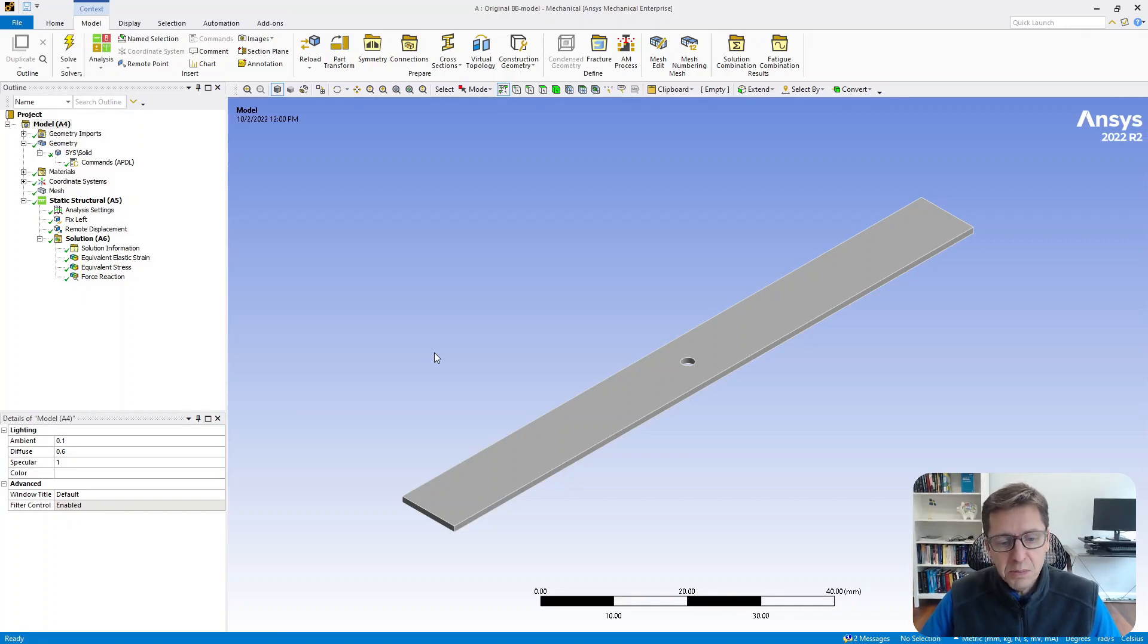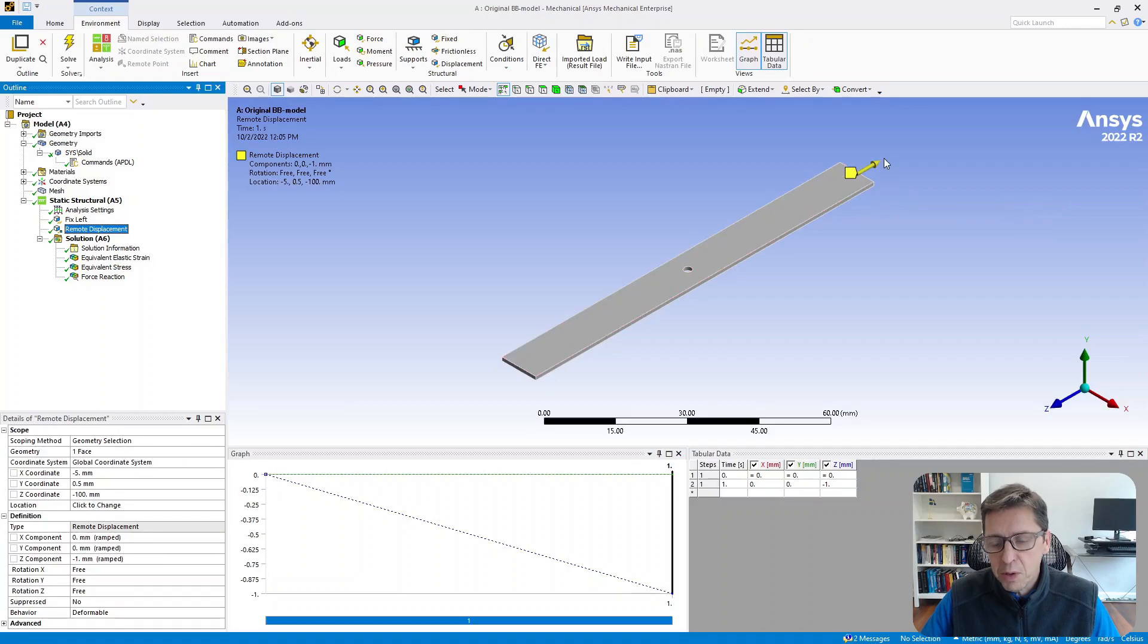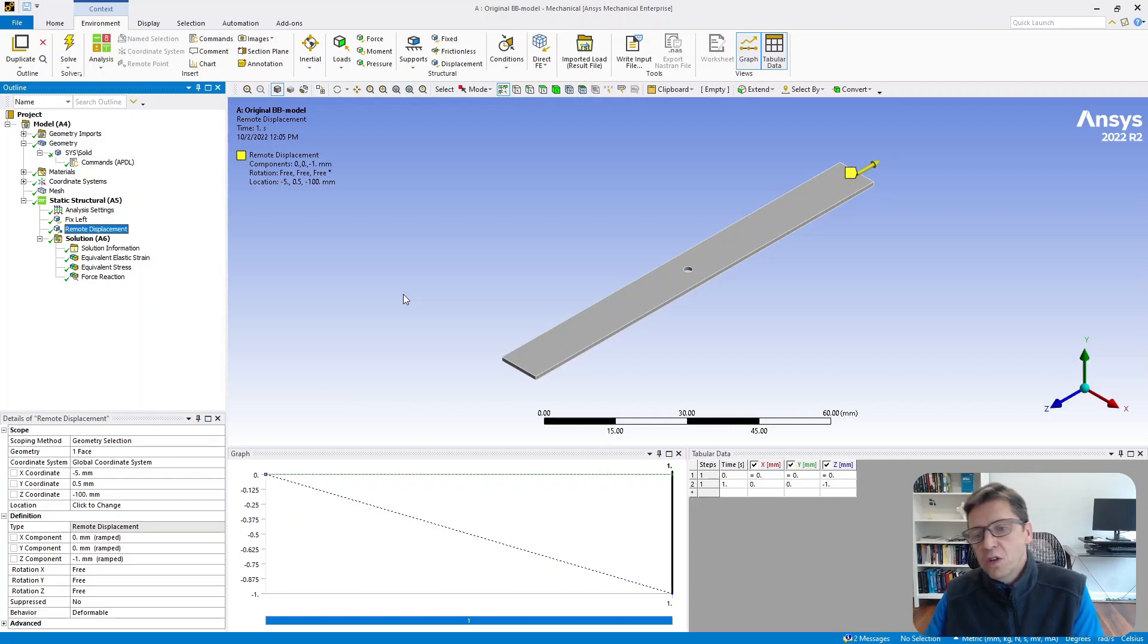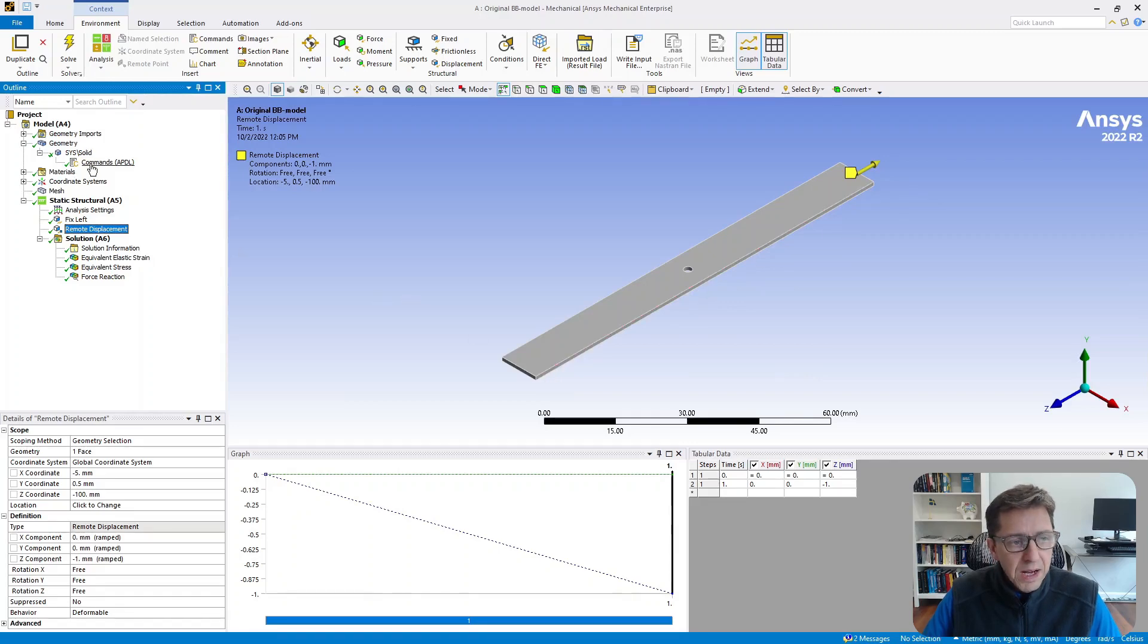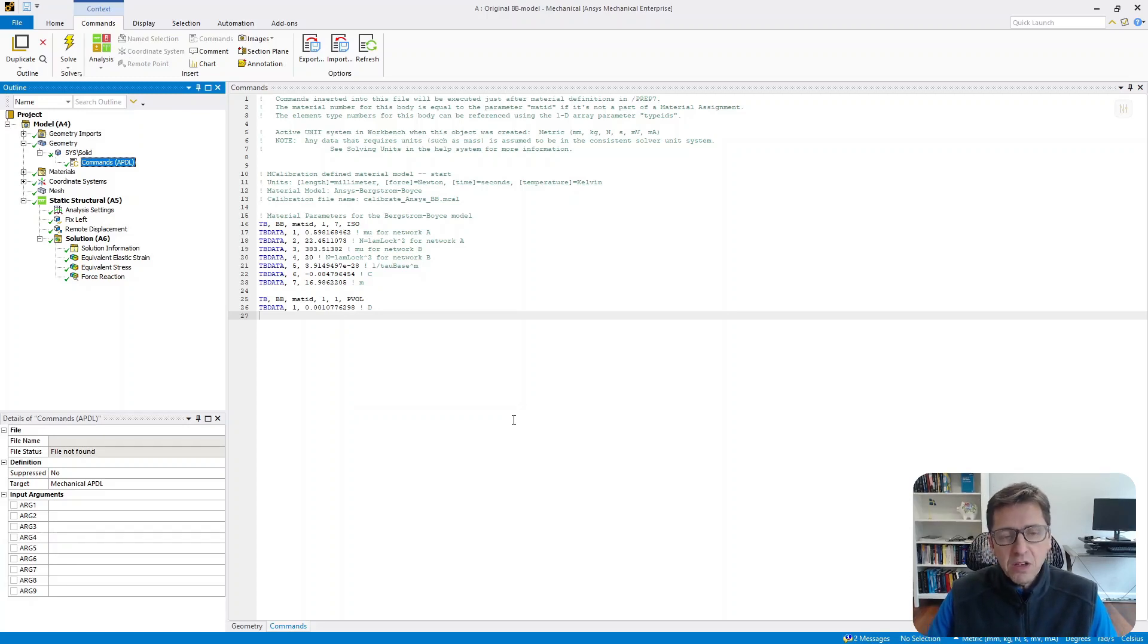So then I export this material model to ANSYS-APDL format. I'm going to plug it in to ANSYS in the material simulation that I want to perform. So I've already done that. So let's open ANSYS. So there's my ANSYS test that I actually ran an experiment on the same CPVC material. It's a strip of the material with a hole in the middle. And I'm pulling this in tension here. I'm basically pulling it out a bit. And I want to predict the maximum force it takes to pull it a distance, in this case, of one millimeter. And this is a 100 millimeter long strip. The material model I plugged in here under solids, geometry, solid commands. And here's the material definition that I got from MCalibration that specifies the material model.